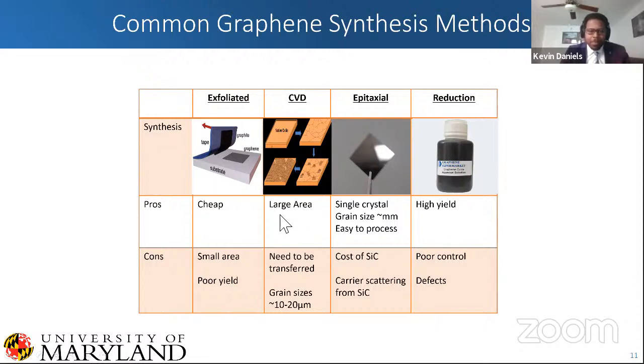One means that's actually also pretty cheap is doing a CVD route, where you take copper or nickel, and you can synthesize graphene by flowing methane across these metal films. But you have to transfer it off this very conductive metallic substrate, and the grain sizes are pretty small. Now, another means is through reduction. You can take graphene oxide, spin coat it onto a substrate and dry it, and then you can reduce it to form graphene. But again, you have pretty poor control over different defects.